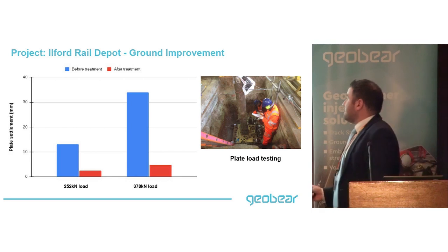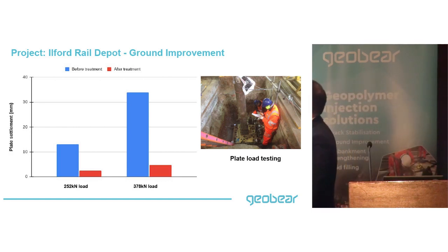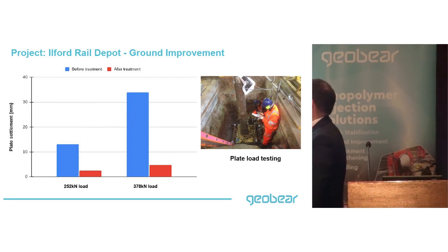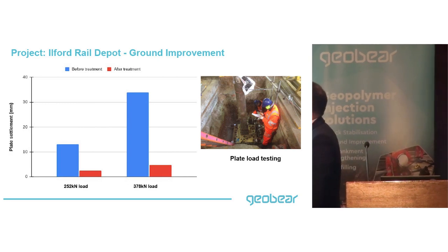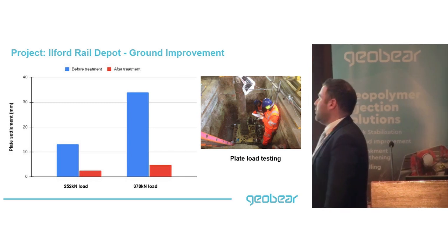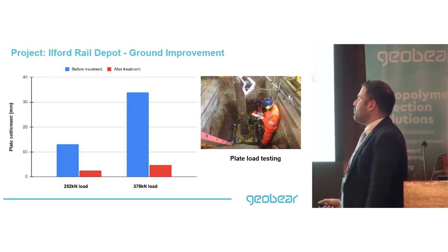This is the testing taking place. Before the treatment, they tested at 2 different loading levels at 252 kilonewtons and 378 kilonewtons. Before the treatment, the low loading was generating a settlement or deformation of around 14 millimeters. After the treatment, it went all the way down to around 4 millimeters.